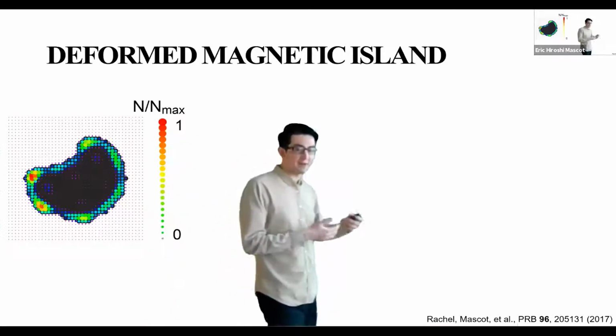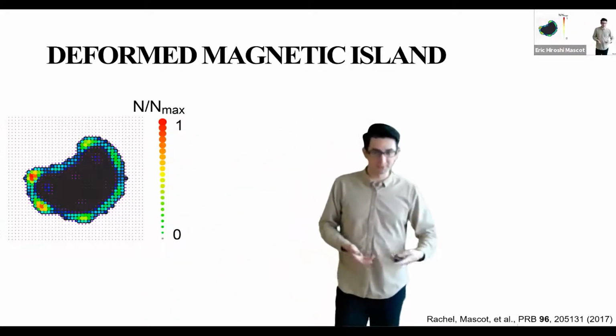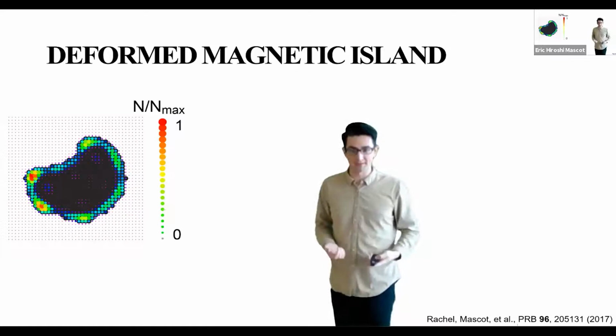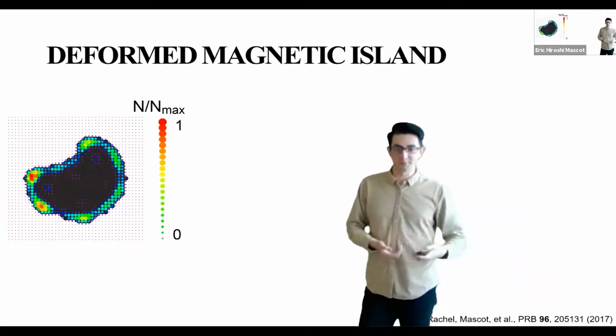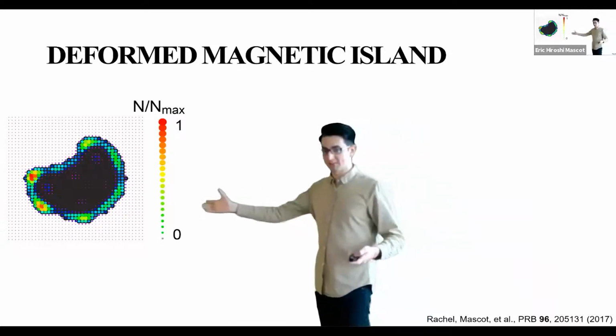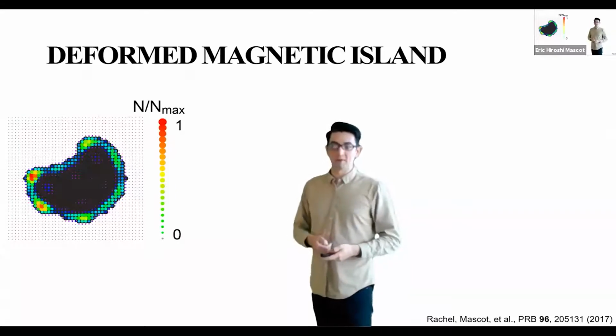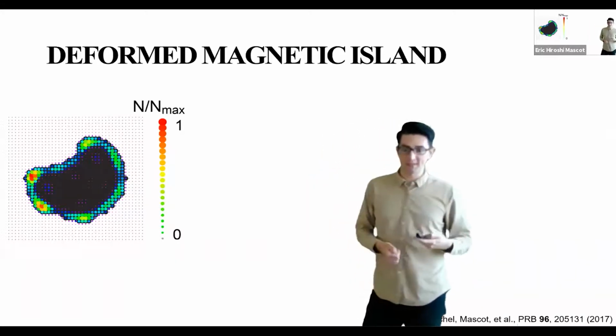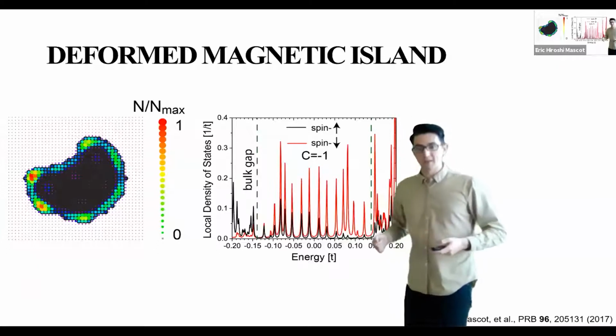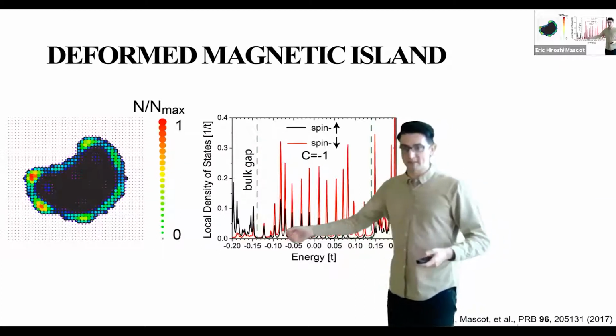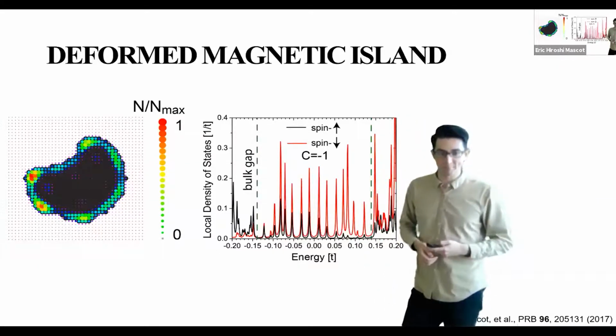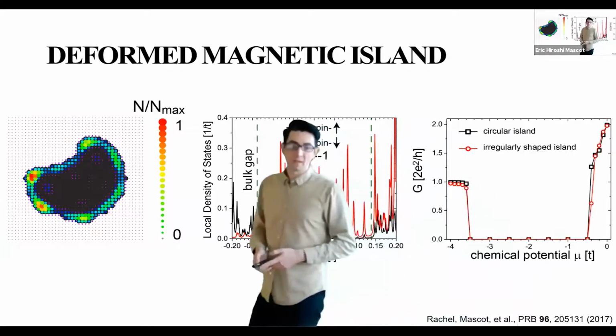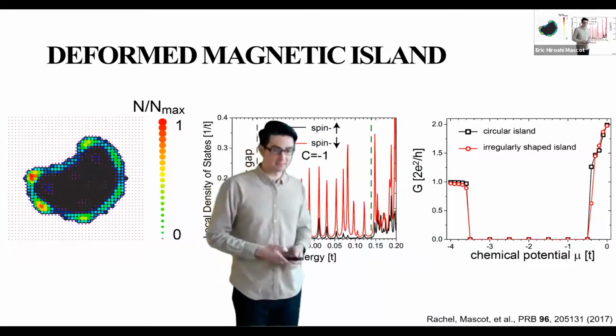And it shouldn't matter, this is a topological superconductor, it shouldn't matter the shape of the island. So we looked at a deformed magnetic island, and we also see that we get a Majorana zero mode localized at the edge. The LDOS has states that go across the superconducting gap, and the conductance is quantized.